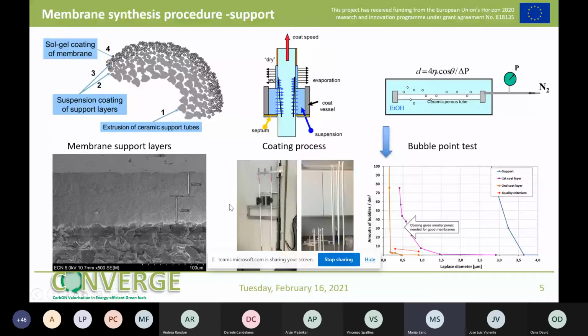You can see here in this picture of the cross-section of the membrane that you have a really coarse support, and then we typically apply 1 or 2 intermediate layers before we apply the membrane layer on top. We are using a coating process to do that. Here is a schematic of the coating process with the coating vessel, and a tube that goes with a certain speed through the vessel. And here is a picture of the setup. We can make membranes up to 1 meter length.